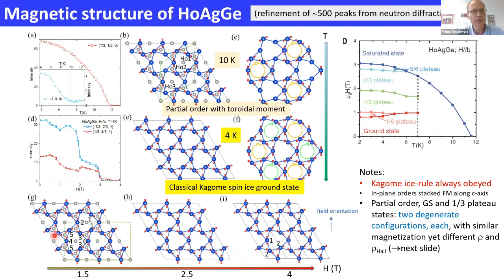And without going into too much detail in this short talk, I'd like to mention that in all these configurations sketched here, in all these 4 different states, the spin ice rule is always fulfilled. So you will see that always 2 spins are pointing inward and 1 outward, or 1 spin pointing inward and 2 pointing outward, for each triangular unit. And these different states are twofold degenerate with a similar value of the magnetization. But most interestingly, we see that they yield different values of the resistivity and Hall resistivity.